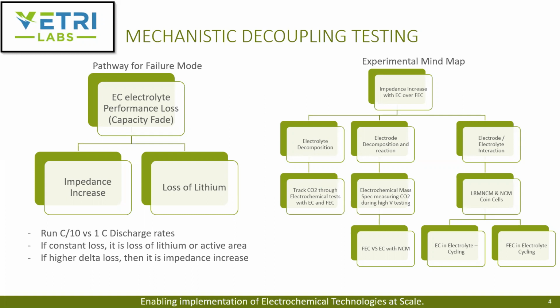By running C over 10 and 1C discharge rates as a function of cycle life, they are able to ascertain if it is impedance rise or if it is due to active area or loss of lithium as a mechanism. For example, if the loss between the C over 10 and 1C discharge rate is constant, it is possibly due to lithium loss or active area. If the delta keeps increasing between the C over 10 and 1C, then impedance plays a role. That's how they separate the two.